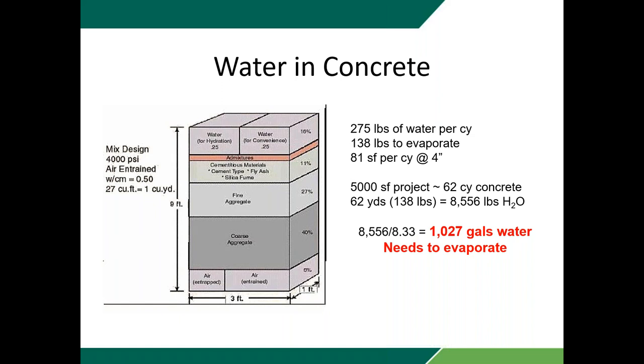The most important thing that I can tell anyone about concrete is, in a given yard of concrete, about half of the water that's in that concrete is going to evaporate or go away. When I pour a yard of concrete, half of the water that's in there is just to hydrate the cement and create that reaction. But if I don't have enough water in there, I can't get it down the chute of the truck, and I can't get it placed, and I can't get it finished. So half of the water in concrete is there for what's called convenience. And that half of the water does not get bound up in chemical reaction and is subject to bleed and evaporation, which are basically the ways that it leaves the concrete.